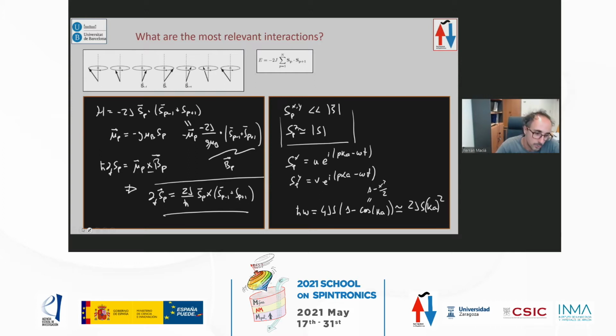And this is important, because probably you've heard that the spin wave dispersion relation goes as k squared. And this is different from phonons and from electromagnetic waves, right? Normally we have a linear dispersion relation, and we have seen right now that if we have spin waves with exchange interaction, what we get is that frequency goes with k squared. And this is one of the main differences.